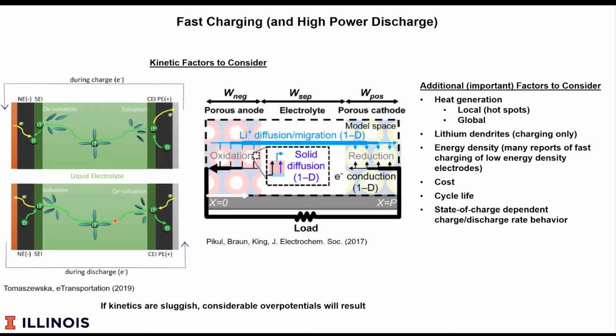So there's many ways to model this. You can look at the paper here by another group or a paper from my group. But if you look at these systems, you can break up the anode, the electrolyte, and the cathode into various model spaces and put in parameters that account for diffusion constants, solvation and desolvation kinetics, ion mobility, electron mobility, and so forth. Using these models, you can get some idea of what the rate limiting steps are. But what fundamentally appears to be rate limiting during fast charging is the lithium dendrite formation.